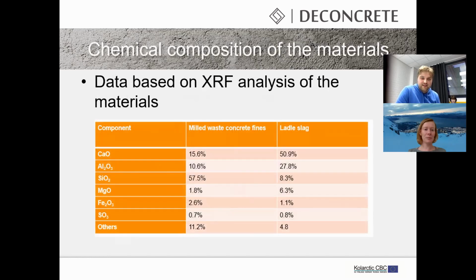And here are XRF analyses of this concrete fines and ladle slag. And as we expected, it contains calcium, aluminum and silicon mostly.